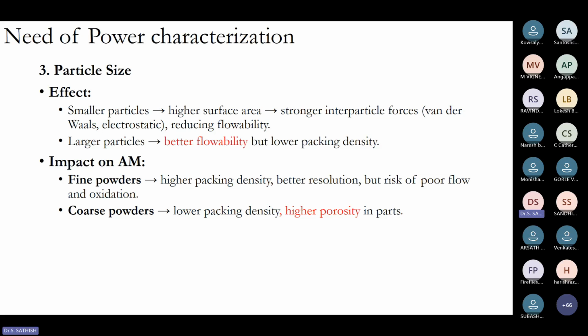So this will impact additive manufacturing. If the powders are fine, that is, smaller particles, it will help you to obtain a higher packing density and better resolution, but it has a risk of oxidation and poor flow in some cases. When you move to coarse powders, you get lower packing density, it won't spread uniformly, and it will result in the formation of higher porosity in the additively manufactured parts.